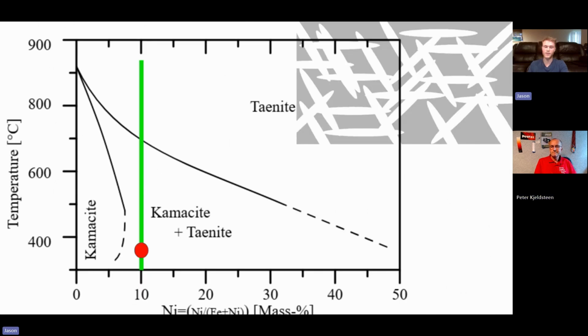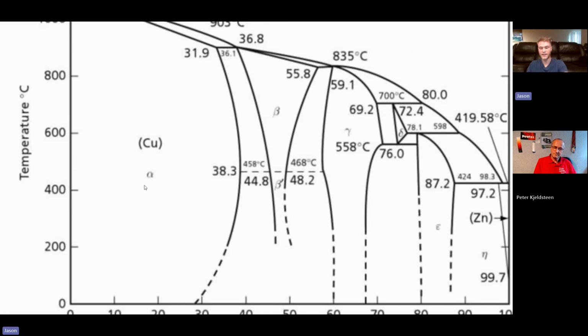So if we look at the iron-nickel phase diagram again, you see we have taenite. Then if we cool in a straight line down from taenite, we pass directly through a kamacite-taenite region. If we look at the copper-zinc phase diagram, we have a very similar story. If we cool down from beta, we can pass through an alpha-beta coexistence region. Yeah, exactly. So it's a very similar solid-state phase transformation in terms of just one phase to another. So the thinking is, if I can cool from a melt, I can start with all beta.